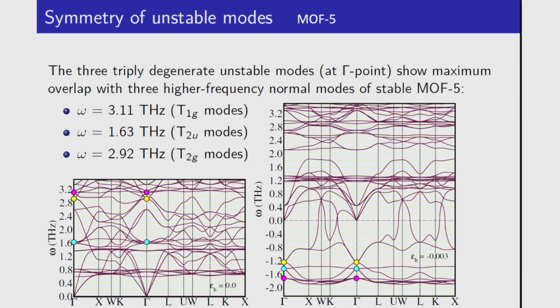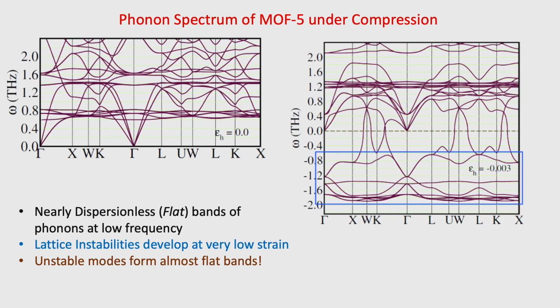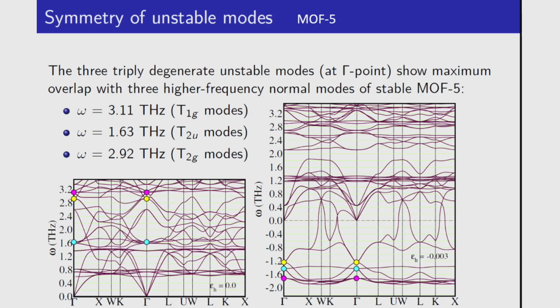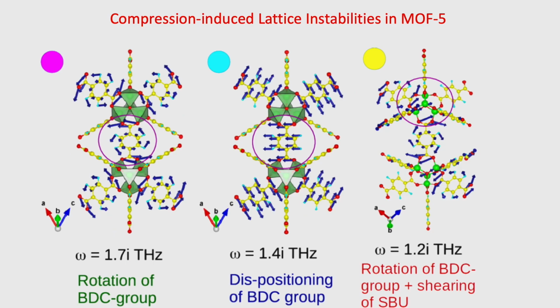So that's what happens. And then we also look at those modes. Basically, the idea is where are these modes coming from? They must belong to some modes on the left-hand side, right? And that's the analysis we did. We basically are coloring them up. These are the modes in the stable structure of MOF5, which become unstable when you apply very small pressure. And those modes have symmetry, these modes don't preserve the symmetry of the lattice. Okay? So those unstable modes will lower the symmetry, and that's what would happen.